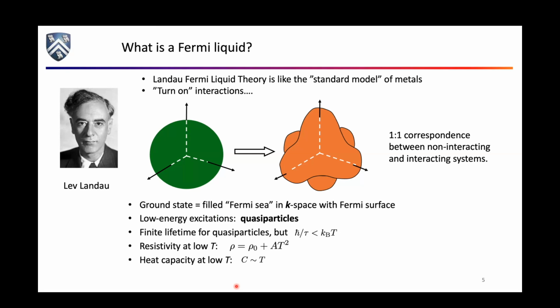They have a finite lifetime because the residual interactions between the particles broaden these things out in terms of having a lifetime. But parametrically, these quasi-particles are always distinct from the Fermi surface. As you cool down, the lifetime becomes longer and longer and longer. The broadening of these states becomes less and less and less. And quasi-particles are always well-defined. And for the same kinds of arguments, particularly if you're in a lattice and you're willing to throw in Umklapp scattering, you can readily see, well, it's a little subtle, that the resistivity is going to have some residual term and a T-squared term at the lowest temperatures. And there's a T to the 5 piece involving electron-phonon scattering. And again, the heat capacity goes like this.